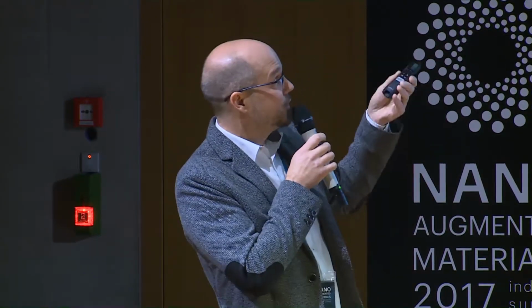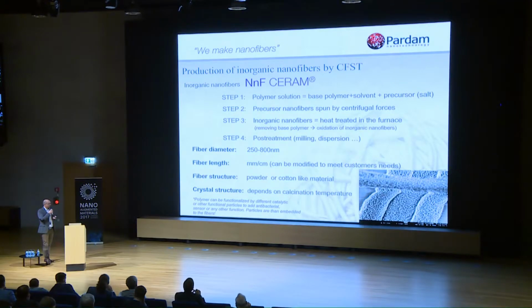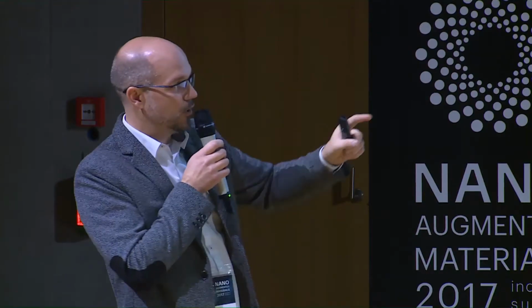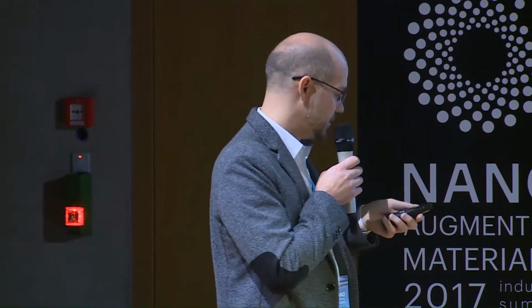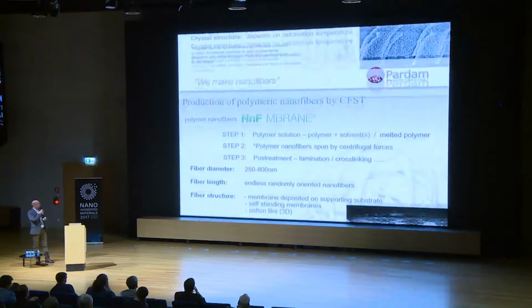The advantage of this process is that we can functionalize nanofibers with high surface area with some active materials, nanoparticles, for example silver, palladium, platinum, whatever. We can add the particles directly within step 1 into the solution and spin it. So after calcination, the active particles are incorporated in the structure of the fiber. Because we speak about mesoporous fibers, they are accessible even though they are inside of the structure. So this is about ceramic nanofibers.